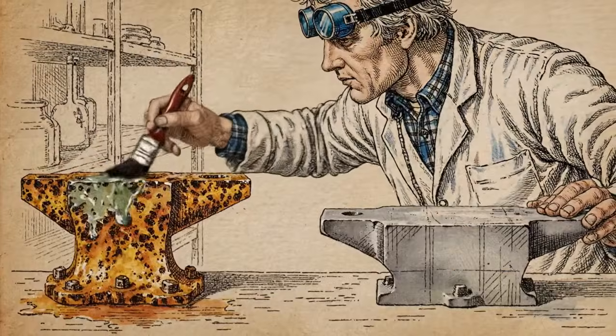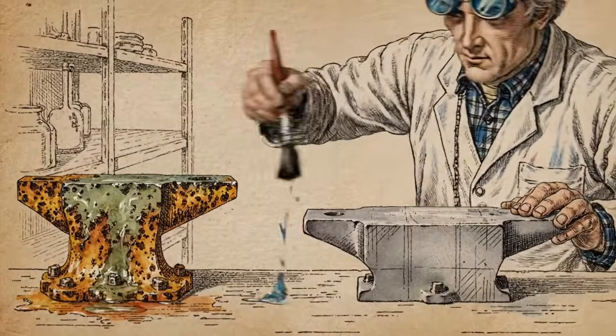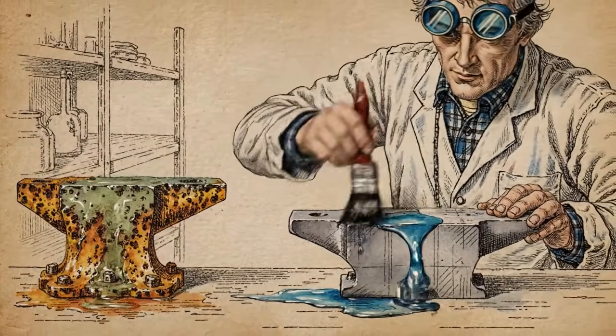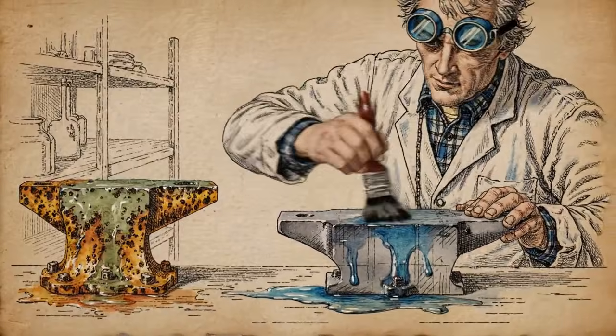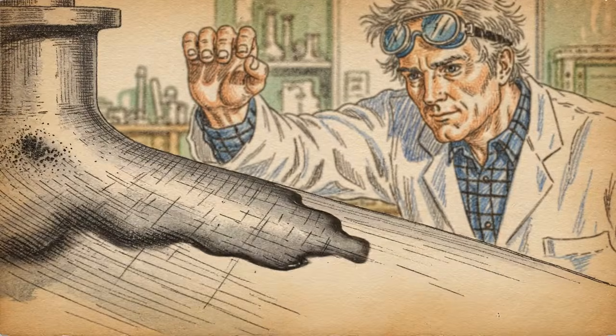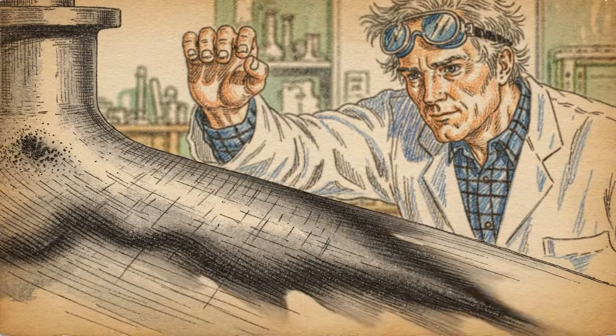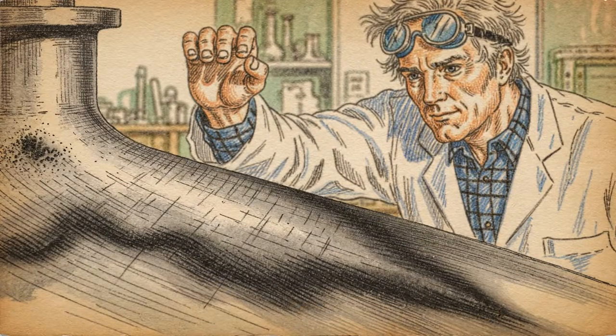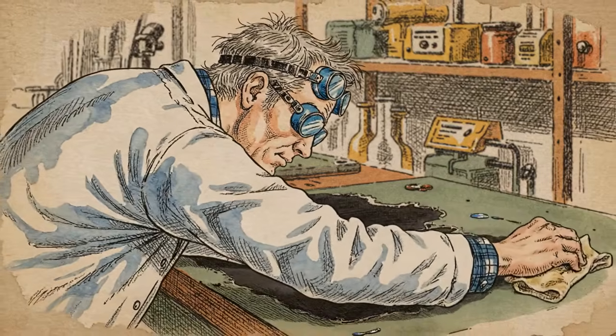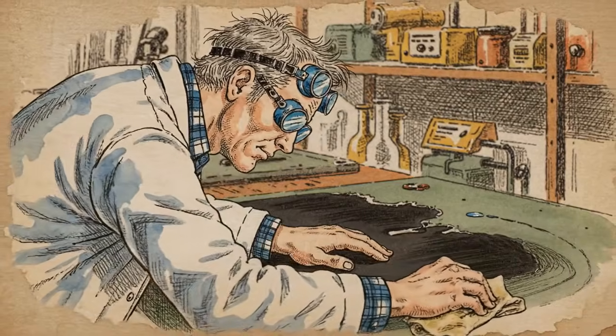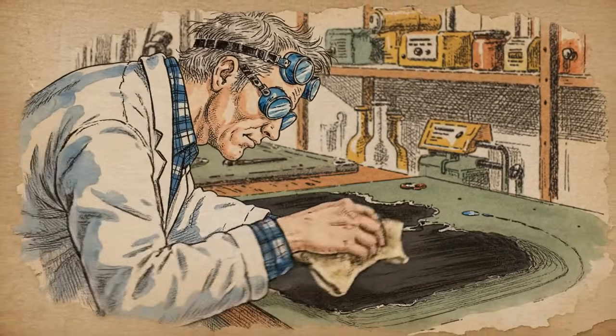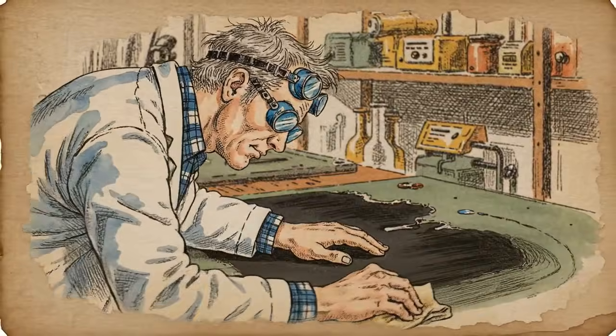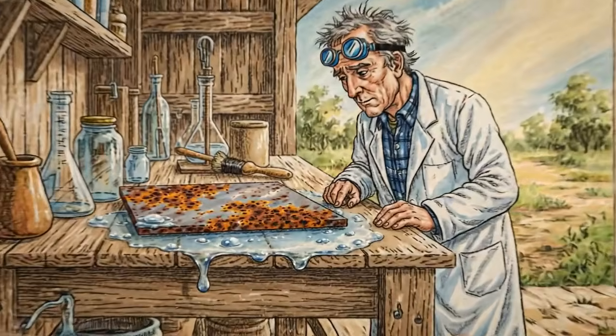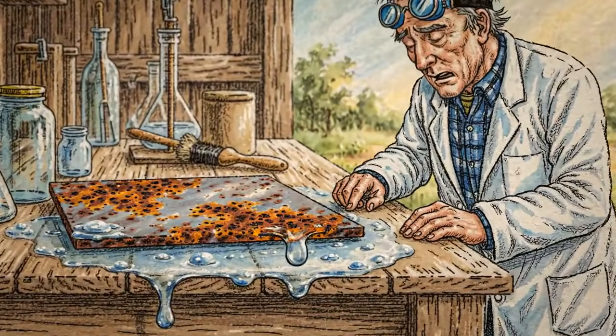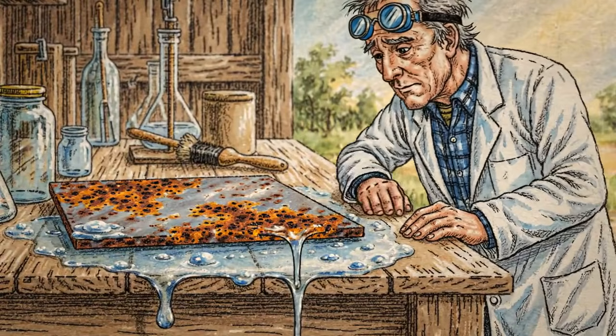Here's the one thing most people get wrong. It is the entire reason this technique has a reputation for inconsistency, and it is the reason I planted that warning at the beginning of this. They wipe the acid off too soon. That sounds too simple to matter. It matters completely. When phosphoric acid contacts iron, bare iron or rusted iron, it begins converting the surface to iron phosphate. The reaction is visible. The metal darkens. A gray to matte black patina forms, and most people see that color change and assume the process is done. They wipe it off at 4 or 5 minutes.